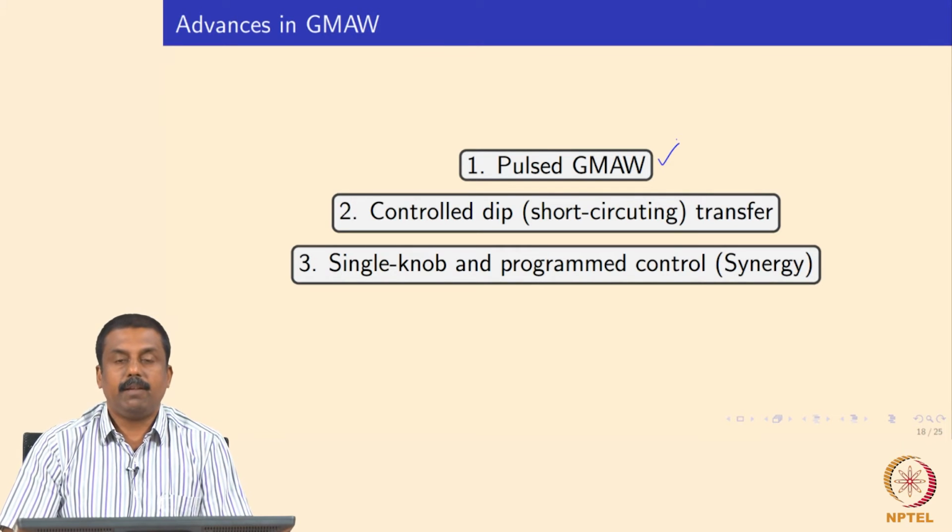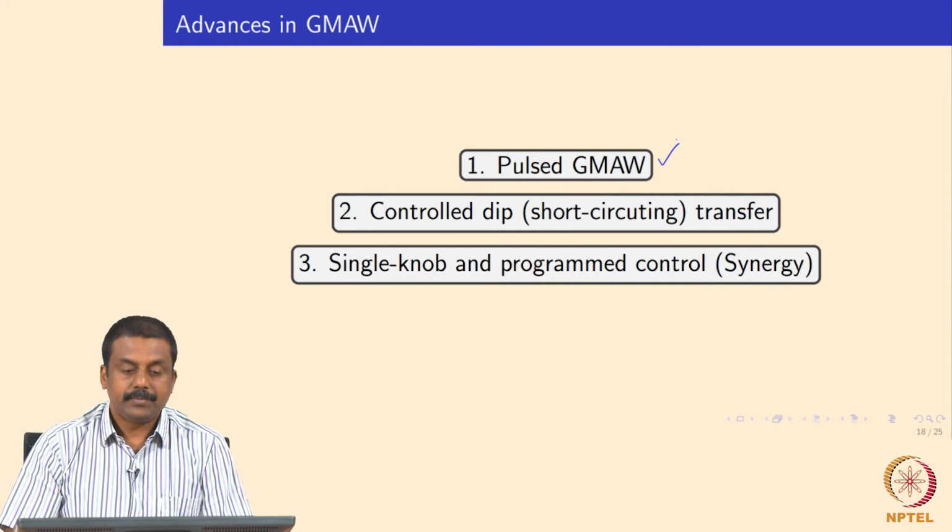For automotive applications, this is also used as a favorable process, because we reduce the heat input significantly by reducing the mean current. So obviously, even if you use a lower mean current, because of the pulsing of the current or voltage, we may still get a spray transition achieved at the workpiece to transfer the droplet in a spray transition mode. And the other development we have